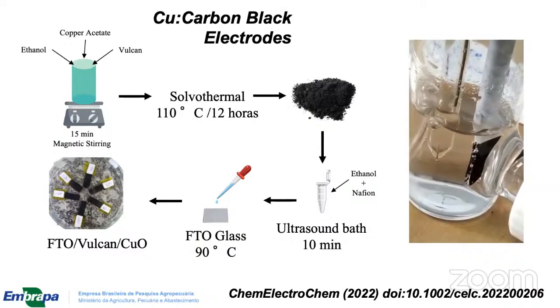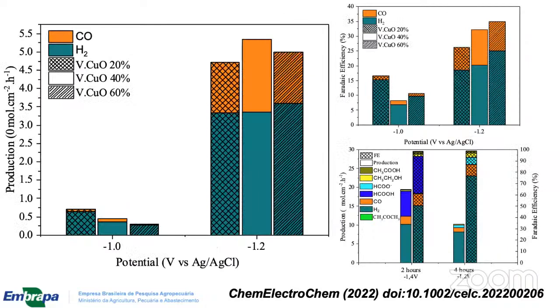But the most interesting part of this system is to understand the Faraday efficiencies of CO2 reduction over the system. So far, our problem is how to control the Faraday efficiency, to control the preference of the system to reduce CO2 instead of reducing water. So although we have a good performance, a good current density of these electrodes, we are still producing too much hydrogen. You can see that we have a high production of hydrogen in these systems. But since we have different conditions to produce this using different potentials, we can tune the system to produce more liquid hydrocarbons.